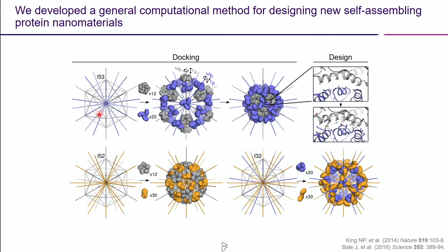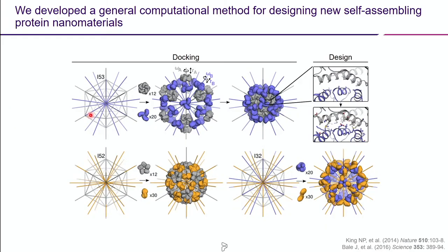Just to walk through this briefly, everything we do makes use of mathematical symmetry. We're building these materials the same way that nature does. The vast majority, 99% of self-assembling proteins, self-assemble according to mathematical symmetry groups. In this case, we're using icosahedral point group symmetry, which contains fivefold and threefold rotational axes. So we find protein building blocks that match those elements of symmetry, for instance, this gray pentamer and this orange trimer that have fivefold and threefold symmetry, and we align those along the corresponding symmetry axes in